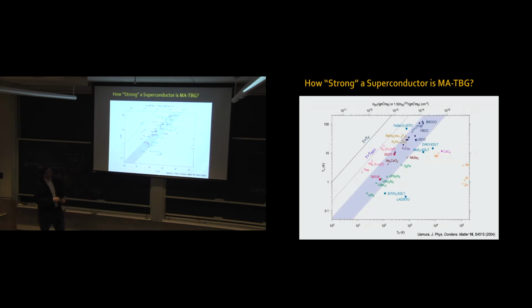Now, you don't usually compare superconductors based on their absolute value of the critical temperature. That's of course very important for applications if nothing else. But the way you typically compare superconductors is you say, how high is the critical temperature for this superconductor given how many electrons it has that can contribute to the superconductivity? And this is typically plotted in something called the Uemura plot. It's a log-log plot of critical temperature versus density properly normalized by degeneracies and effective mass, or you can think of it as Fermi temperature.